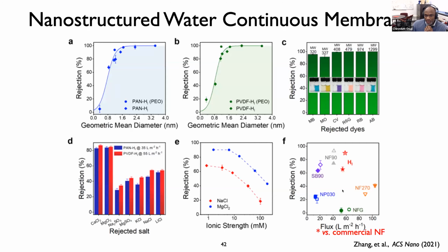The results from transport characterization are attractive and compelling. So this is looking at rejection for these membranes when confronted with polyethylene oxide solutes of different sizes. And this is done for membranes produced on PAN support layers versus membranes produced on PVDF support layers. And the molecular weight cutoff here corresponds, or the size cutoff corresponds to solutes on the order of 1 to 1.4 nanometers. Okay, if you look at rejection of molecular dyes, the molecular weight cutoff is maybe in the region of 400 Daltons. But here the transport is affected also by the fact that the dyes are charged and the solid surfaces within the nanostructured membranes are also charged.